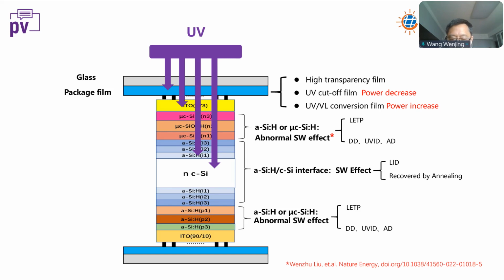For the doped layer, not only the amorphous and the microcrystalline layer, recently some other authors found there's an abnormal Staebler-Wronski effect. It means if we use LETP, the efficiency can increase, but there is a dark degradation, the UVID, and annealing degradation. And for the interface of amorphous and crystalline silicon, there is a Staebler-Wronski effect. It means there's a LID, but if we anneal, it can recover.